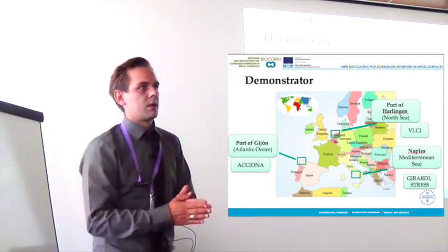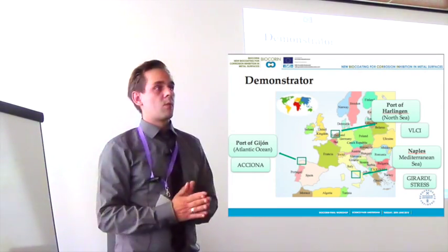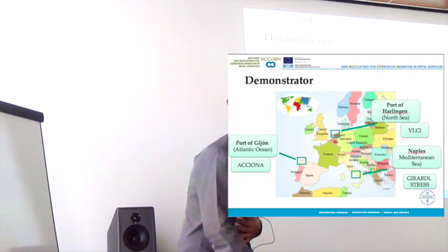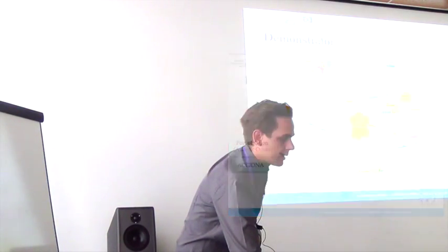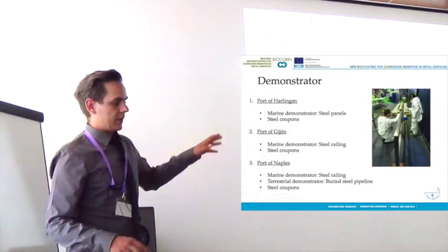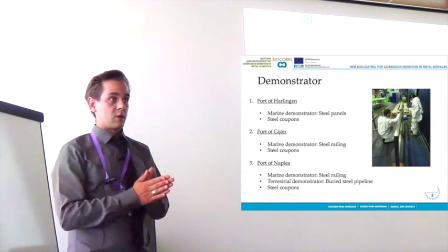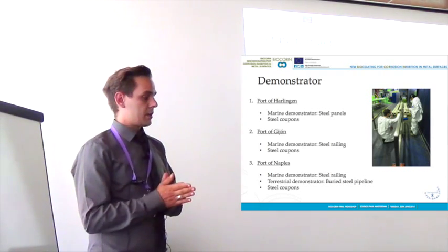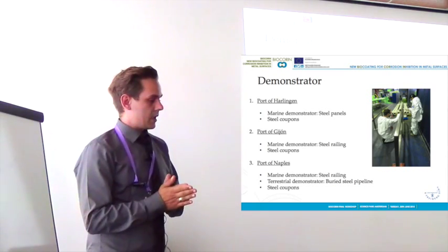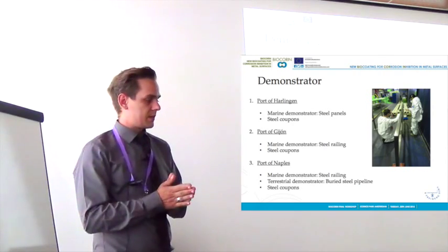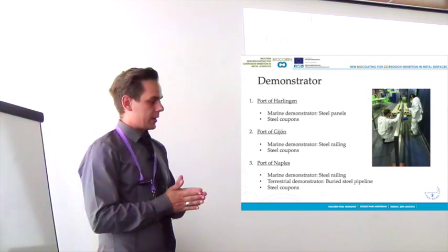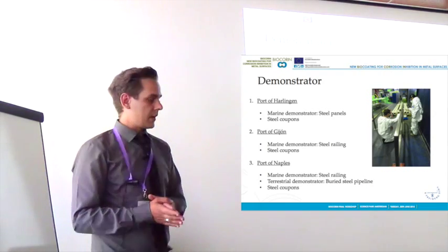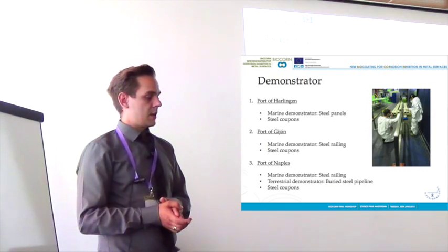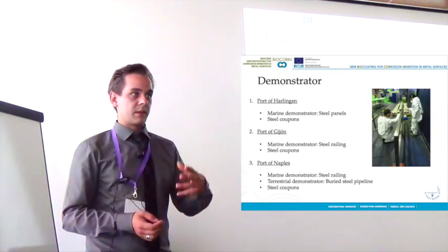These materials, B1 and B2, were upscaled and tested in the demonstrator, and as Rocio said, we tested them in the port of Harlingen, in Naples, and in the port of Gijón. In all of those demonstrator places we tested steel coupons with both materials. In Harlingen and in Gijón we coated some other steel constructions, like steel panels or steel railings, that were tested in the marine demonstrator. And in addition to this, in Naples, we tested a terrestrial demonstrator. A steel pipeline was coated and buried in the ground.